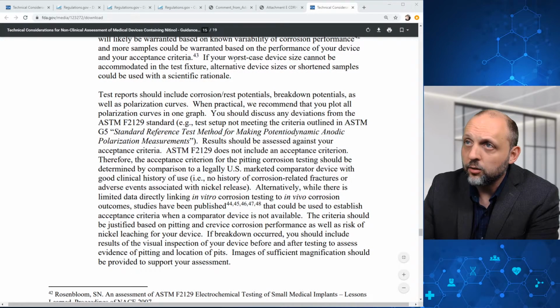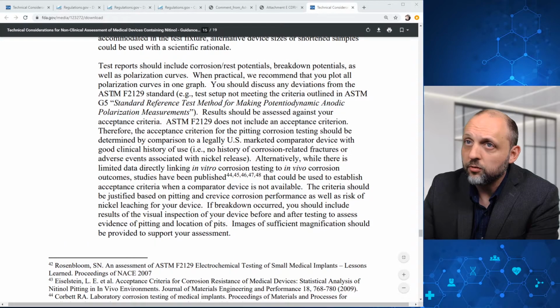Here, FDA notes that if your worst case device size cannot be accommodated in the test fixture, then alternative device sizes could be used with a rationale. And then here, FDA calls out that test reports should include corrosion and rest potentials, breakdown potentials, as well as polarization curves. And when practical, they recommend that you plot all polarization curves in one graph and discuss any deviations from ASTM F2129.